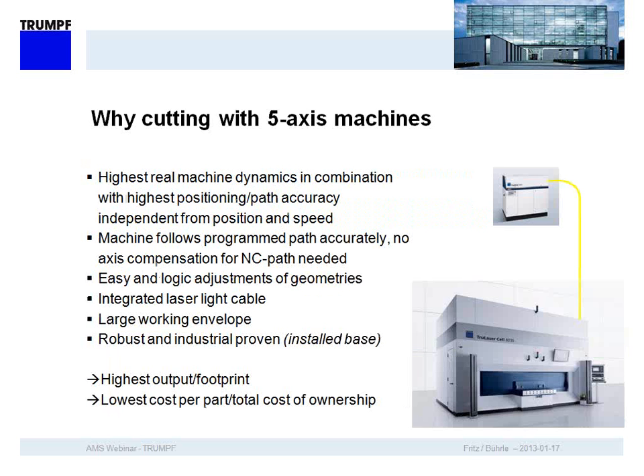So also another thing, why do we use 5-axis machines? Well, we see that there is a need for very high dynamics motion. So a 5-axis machine is pretty much a Cartesian coordinate system where we have very stiff and rigid axes, so we can follow the program path very accurately. So we don't need to compensate for any slack in the axes. Make a program, we can put the part on the machine and then cut it right away with maybe just a few adjustments. Also, if adjustments are necessary in the process, which is always the case, that holes or contours need to be shifted and moved, this can also be done very easily on the machine.